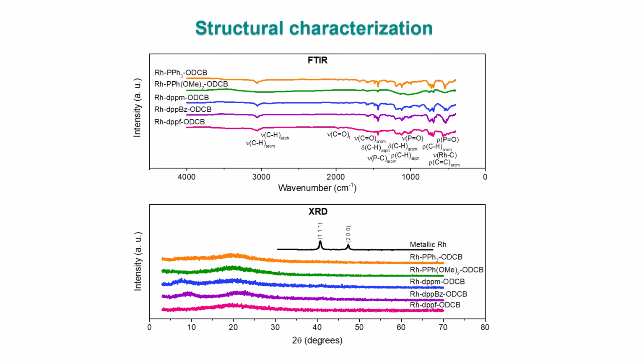The FTIR spectra confirm the successful synthesis of the rhodium carbonyl phosphine clusters. The characteristic carbonyl stretching bands and the signals associated with oxidized phosphine ligands indicate that both types of ligands remain coordinated within the molecular structures. X-ray diffraction patterns showed no peaks corresponding to crystalline metallic rhodium. This indicates that the synthesized materials remain as molecular rhodium clusters rather than forming metallic nanoparticles.